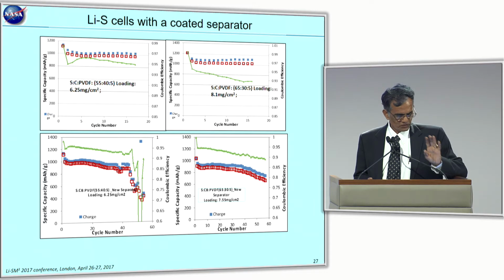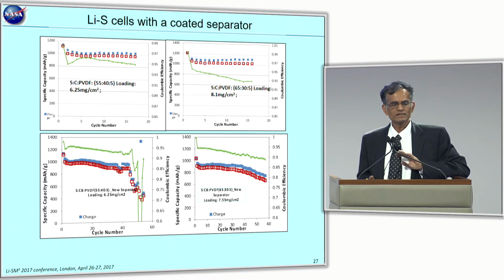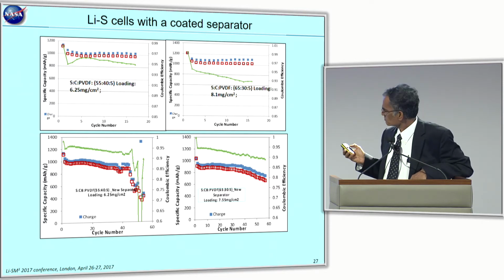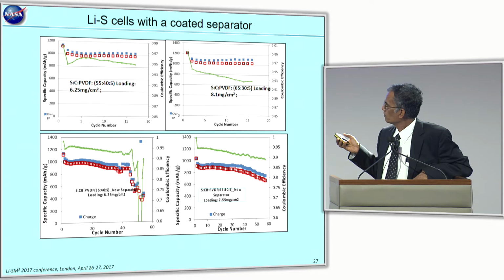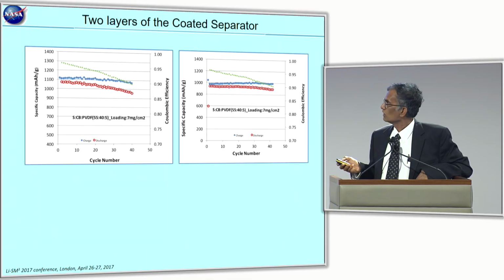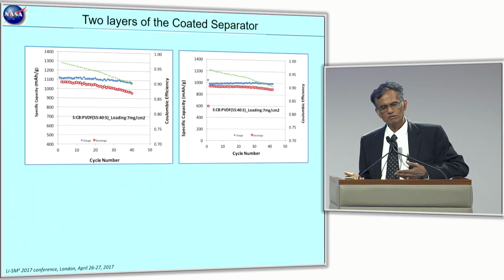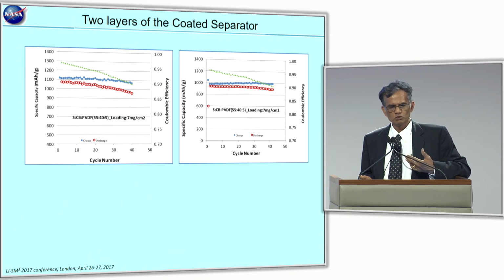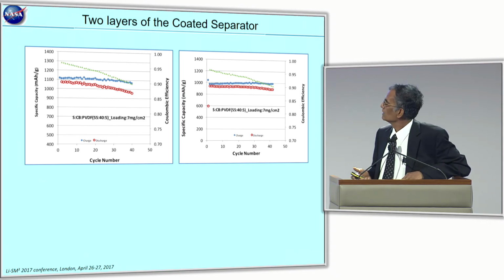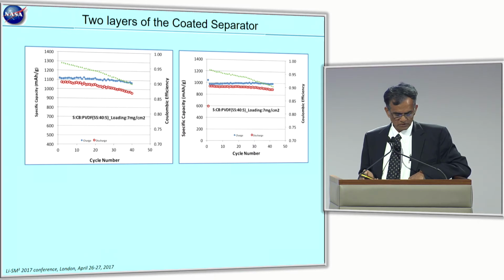And then briefly, just like we have the benefit of blending all these things with sulfides and oxides, we thought we would coat a separator, look at a ceramic coated separator, and sure enough, we have seen much better performance by just replacing the separator with a ceramic coated separator. In some cases, of course, you see some failure around 60 cycles. To mitigate that, we thought maybe we have 2 layers, one on the anode side to minimize the dendrites coming from the lithium, and one on the cathode side to stop the shuttles going into that. And then we seem to have better stability here.